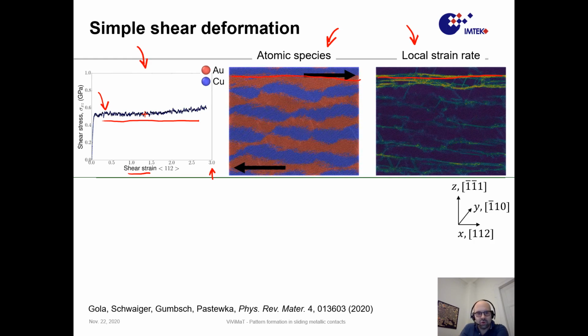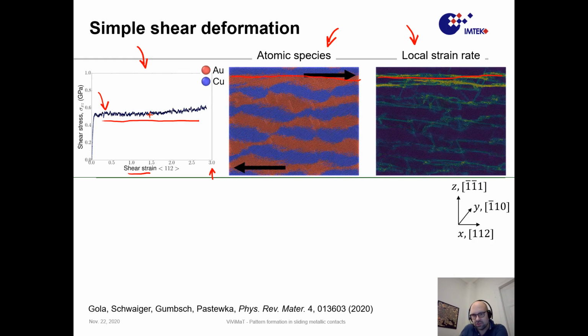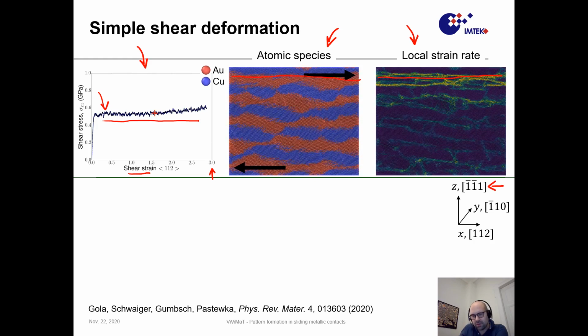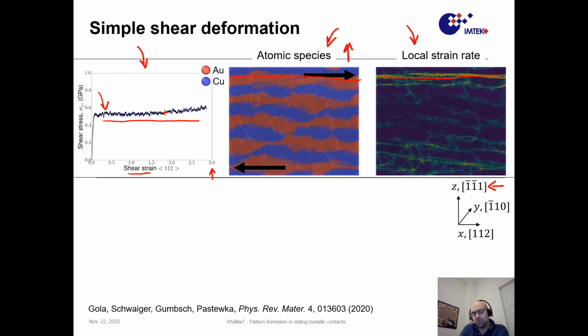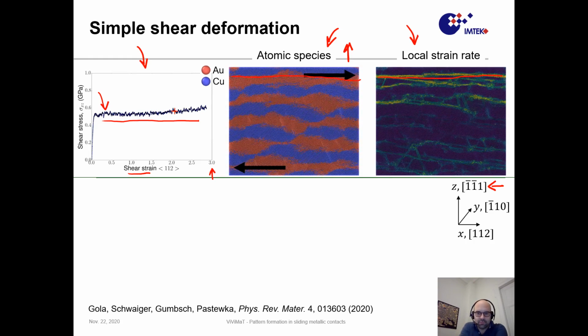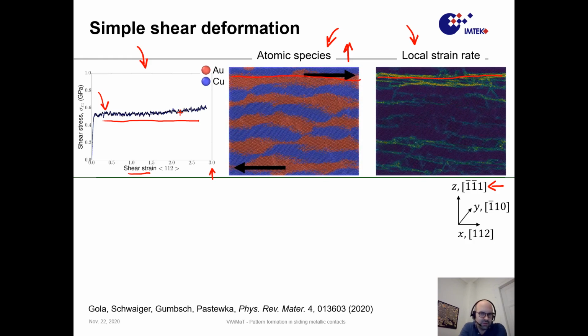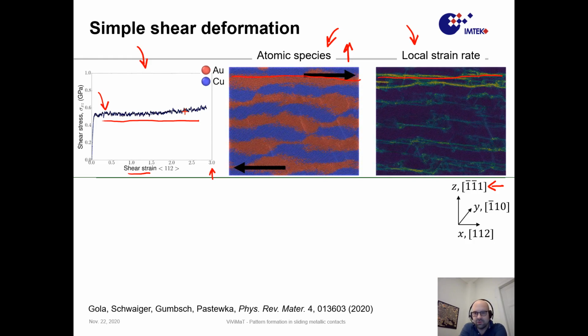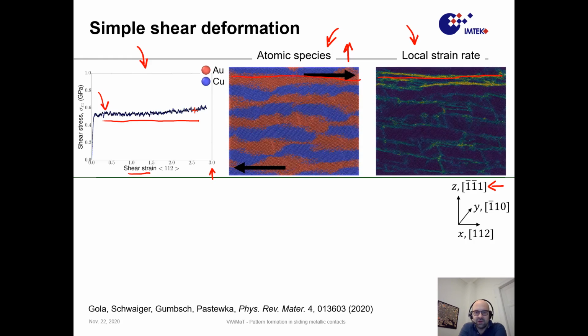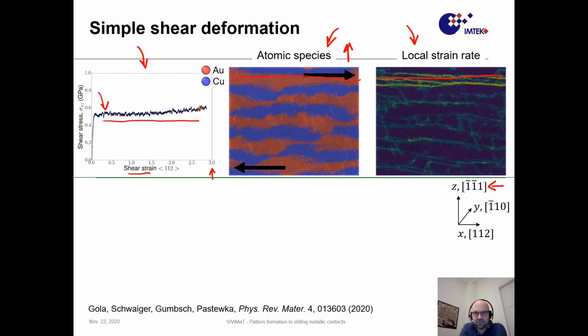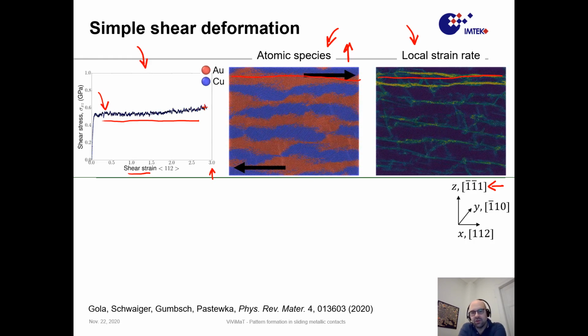This makes sense. I haven't really talked about lattice orientation, but down here I'm telling you that the surface normal orientation, the normal to the interface, is actually the 111 lattice plane, and that's an easy slip plane for this FCC material. So it makes sense that it can deform easily at these interfaces where misfit dislocations exist between these two crystal lattices that have slightly different lattice constants.